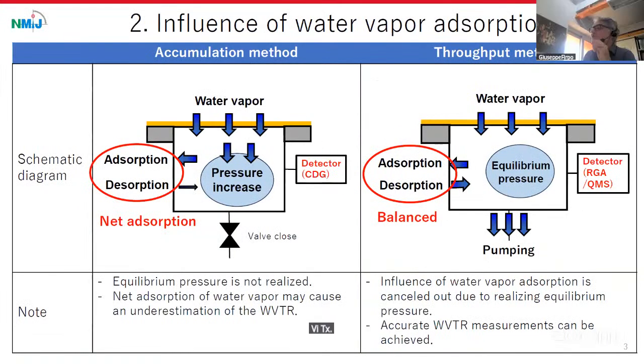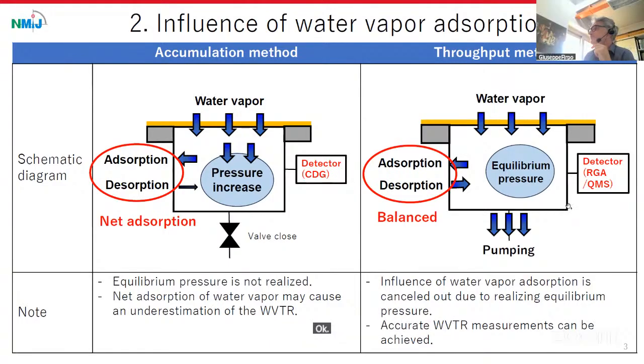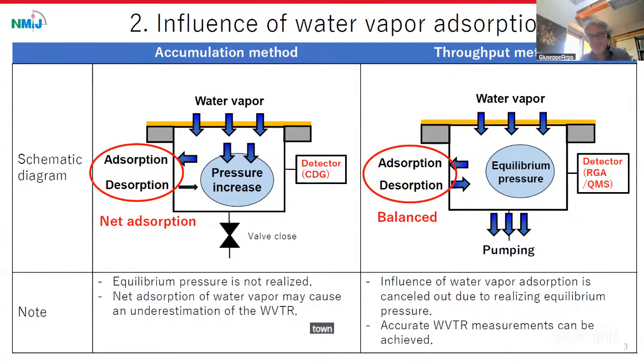Thank you. Have you ever heated the chamber to decrease the adsorption rate of water during measurements or not? Yes, I'm typically keeping the temperature of the vacuum chamber at 40 degrees C. Okay, 40, a little bit higher than room temperature. I have tried higher temperatures, but it doesn't work well. It's very challenging. Yes, very challenging.